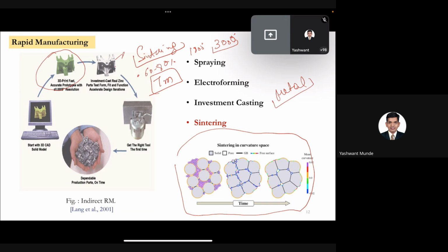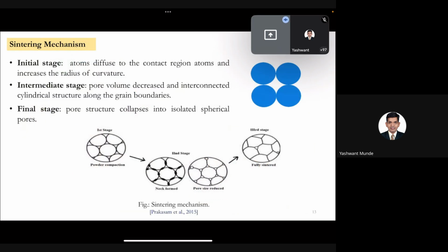Now you don't have a laser. There is no laser. There is no electron beam source. So the joining of the metals is by conventional induction heating, whatever the source of heating in the furnace. It can be a microwave furnace also. But you don't have a laser, which is mainly reflected when you fire it on a highly thermally conductive material like copper. So by combining the polymer 3D printed part and sintering, we can easily make copper 3D printed parts. Let me show you some.